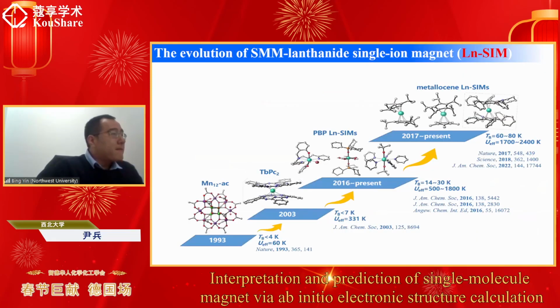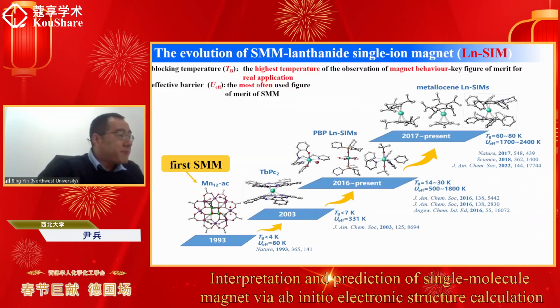And the first single molecular magnet was reported in the year 1993. It's a polynuclear transition metal system consisting of 12 manganese ions of different valence states. There are two important figures of merit to measure the performance of a single molecular magnetic system. The first one is the so-called blocking temperature, TB. It is the highest temperature of observation of magnetic behavior. It is quite important in real application. And the other one, the so-called effective barrier, Ueff, is actually the most often used one to measure SMM properties.